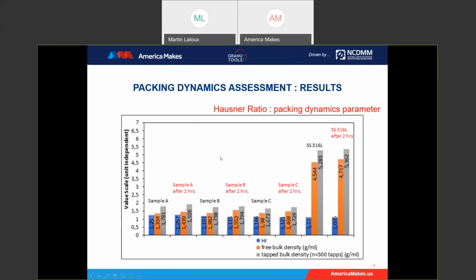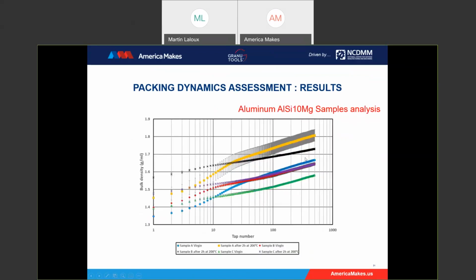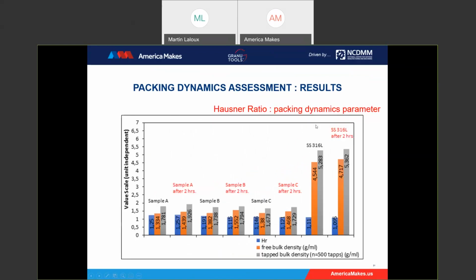Here is a summary of what we saw, and also the comparison of the Hausner ratio. You see sample A virgin and sample A after 2 hours heated up, sample B the same, sample C, and stainless steel. If the powder is heated up, the Hausner ratio decreases. As we can see here, the Hausner ratio is in blue, except for A, because the error bars are too high. For samples B, C, and stainless steel, we observe that the Hausner ratio is decreasing. And this is a similar trend for the tap and bulk density: they are increasing after heating the powder.